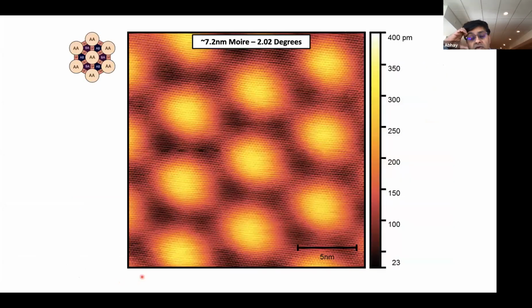So what we did, when these results came out, is we started making these samples. And it turns out that these samples are a complete pain to make, because you try to make a sample with a given angle and nature doesn't want to stick to that angle. It sends it off to some other angle. And roughly 1 in every 10 or 20 samples works, which is very annoying. But what this allows you to do is to get data on all kinds of other angles that you didn't really want to get, but happened in any case.